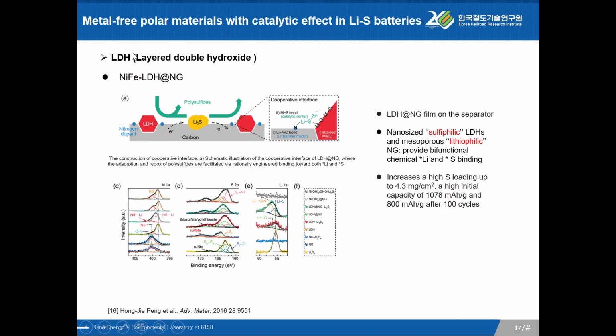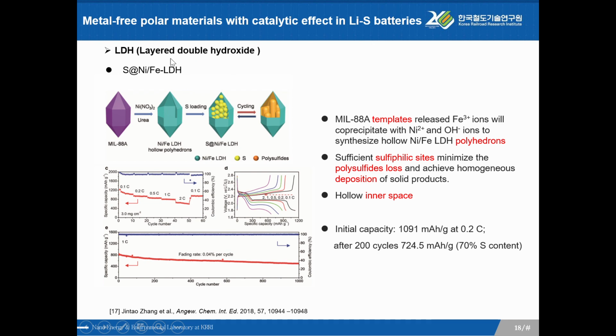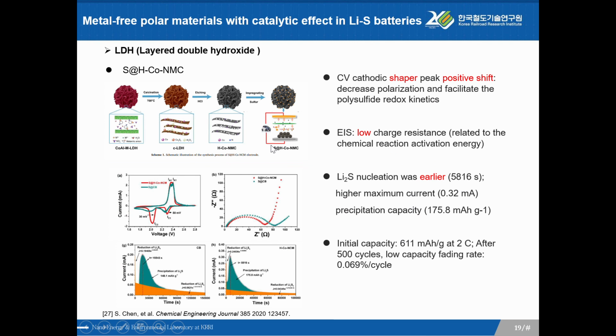This is LDH catalyst. This is another kind of LDH catalyst. Yeah, we can see similar performance. The current density is increased, with positive shift and negative shift, and there are 2 peaks and faster charge transfer, and the nucleation energy is higher.